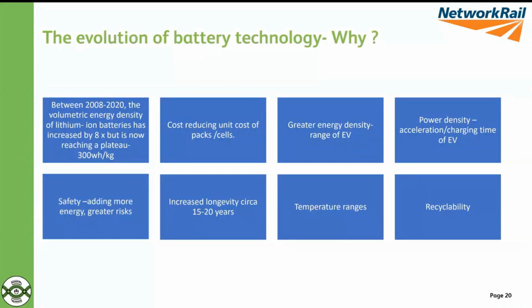I've included this part really to talk about how the technology is evolving, because between 2008 and 2020, in terms of volumetric energy density, we've had an increase of about 8-fold on lithium-ion batteries. So there's been quite a significant move in the industry. But my view is they're starting to plateau at about 300 watt-hours per kilogram. And we want more energy in smaller batteries to increase the range of our electric vehicles, and when we have to charge them, we want much quicker charging. So the technology has limitations.